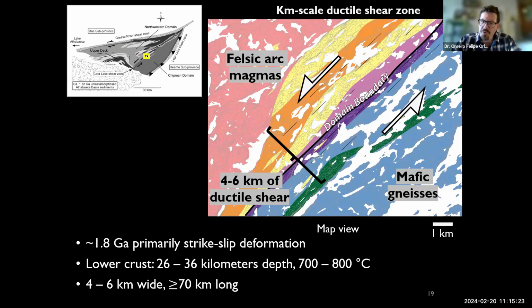When you do thermobarometry on the various mineral assemblages that are participating in its ductile structure, it's really deep and it's really hot. So this is granulite facies, which, making reasonable assumptions about the crust, is 26 to 36 kilometers down, 700 to 800 degrees Celsius. And just at this one exposure, it is 4 to 6 kilometers wide as an identifiable ductile structure, and at least 70 kilometers long before it gets truncated by other stuff. So it is a big lower crustal ductile feature.